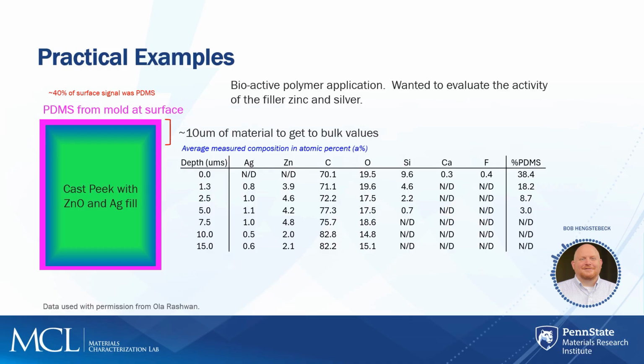As it turns out, the GDMS allows us to see layering into the material. And so initially, after we remove the PDMS, we still don't see very much of the silver, the zinc. And then in that near surface region, we do see a lot more of the zinc filler and the silver filler. We also are able to preserve the chemistry. So we know that the zinc is in the +2 state and the silver is primarily in the +1 state, which is what they wanted to see in this material. And then as we go deeper into the material, we actually will see that it goes down towards what they're expecting in terms of bulk composition. So the process did allow them to make a more bioactive area once they would do a little bit of surface processing to remove the crust that's being formed during the cooling of the material.